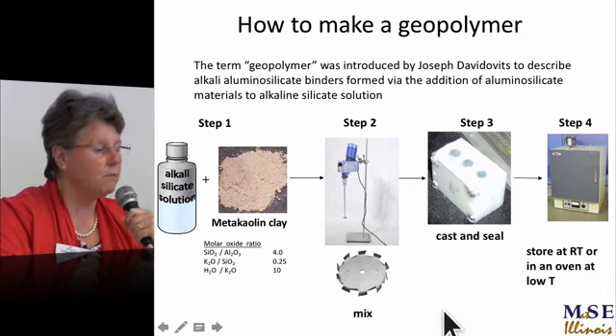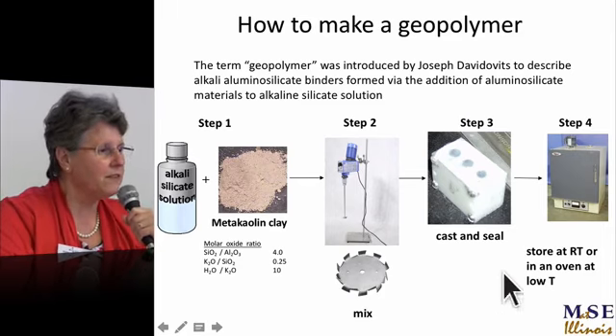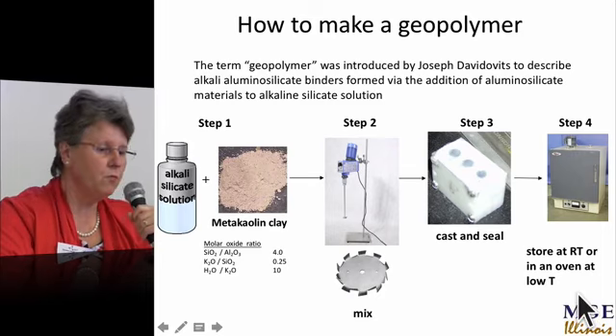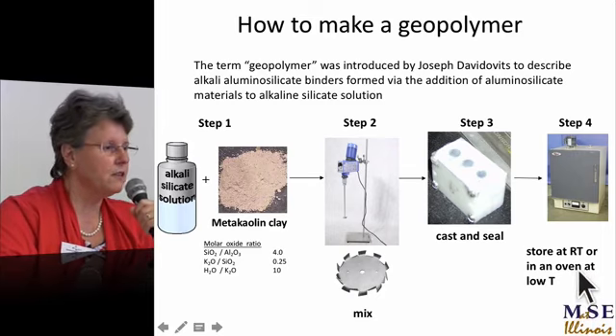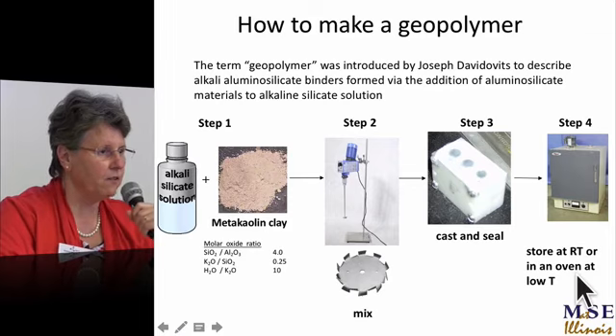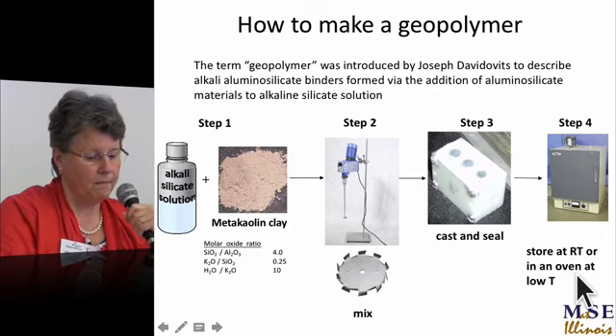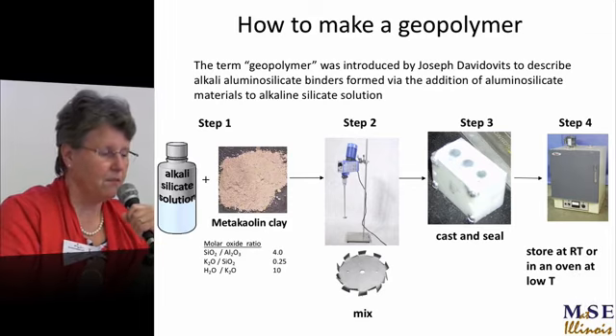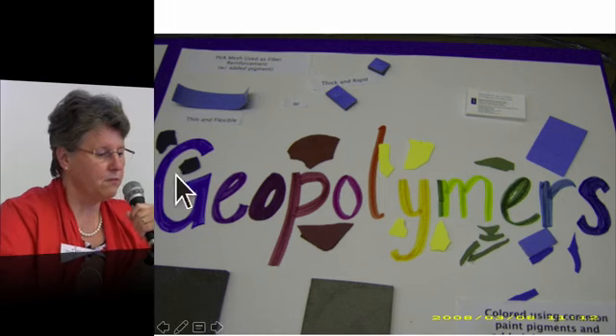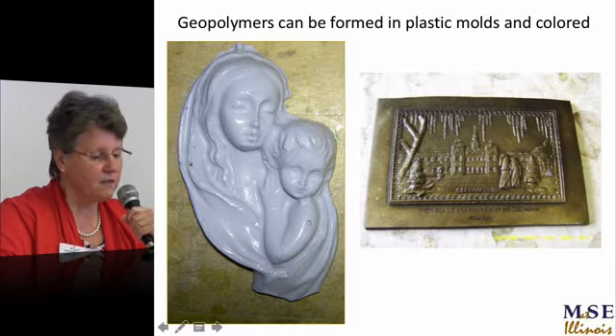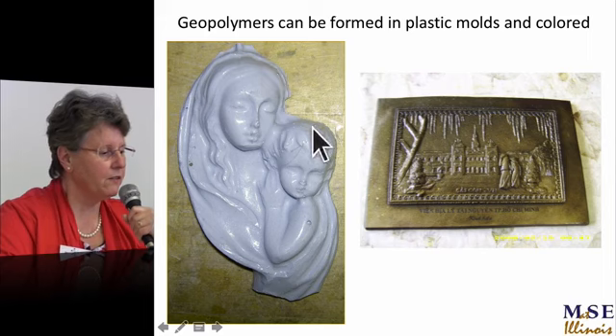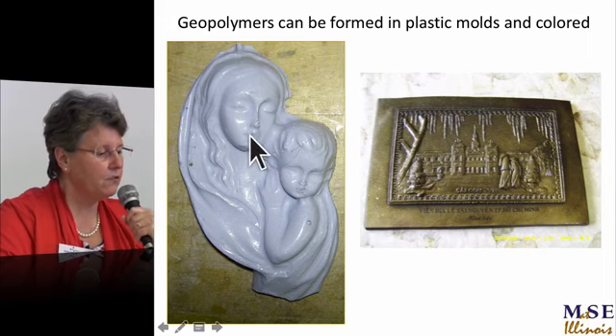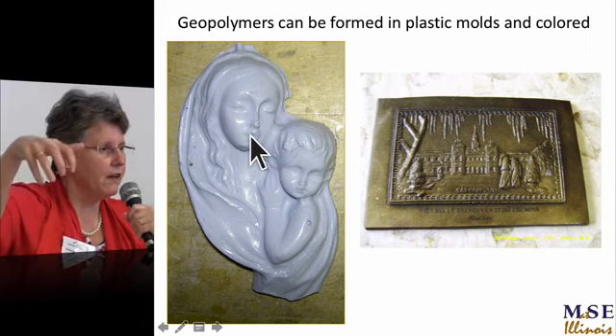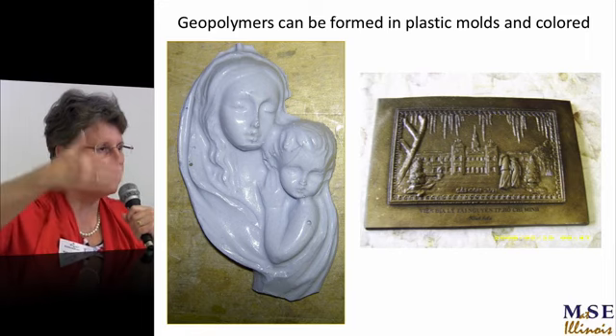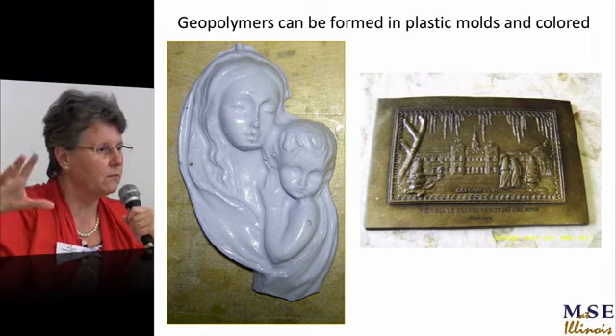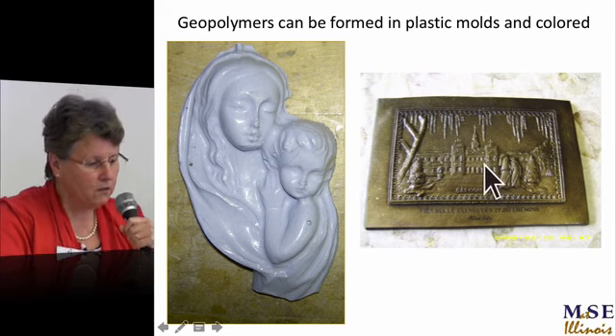And then you put it into a mould and it doesn't stick to plastics. And then if you wanted to, you could heat it to 50 C and you'll get it in 12 hours. But I don't know the properties are quite as good as the room temperature. You can put nice colours in like this, and you can have a nice mould. And there's always the water tries to get out, so that it makes a film at the interface, and you can demold it readily.